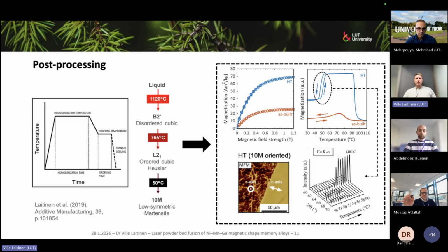On the right side, you can see some examples from materials we have made, actually nickel-manganese-gallium, that has been heat treated after the laser powder bed fusion, and we can get quite nice properties. Saturation magnetization significantly improves after heat treatment. We start to observe the normal magnetic phase transitions also: this circular dashed line is the martensite transformation, and then the Curie temperature is at higher temperature. And then we also get this magnetic domain structure put in place.